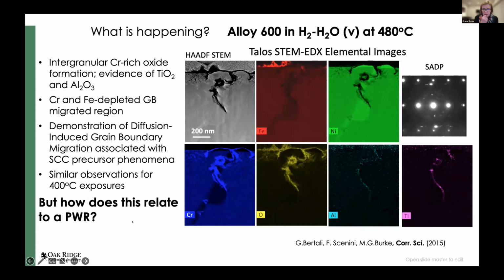When we look at those FIB cross sections using the Talos, we can see very clearly that we have some pronounced chromium depletion. We also have chromium oxide formation, and the nickel map shows this very clearly as well. The boundary has undulated and we've got nickel-rich regions, but also some titanium and some aluminium is present. So we've got what actually is diffusion-induced grain boundary migration, and that's associated with this SCC precursor phenomenon. We're having very rapid diffusion of chromium out of the material to form the surface oxide and then start to oxidize along the migrated grain boundaries.